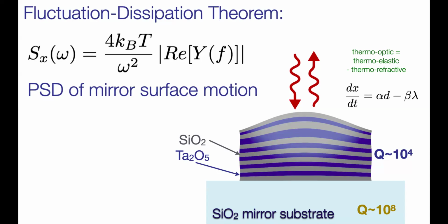It means the photons which scatter off of some sort of transition or atomic system, it also tells you about how much that thing will absorb radiation and couple it back to you. It's just talking about the time reverse symmetry in that system. And the fluctuation dissipation theorem is like this. It says, if you care about the fluctuations of your system, the power spectrum of this motion, that has to do with the admittance of your system and the temperature and the frequency. And the admittance is just the ratio of the velocity divided by the force, if you apply force to it. So you take your system and you squeeze it like this, and you see how much heat is generated. And that tells you how much dissipation is in your system. And that will tell you how much your system will fluctuate. So that's what we do.